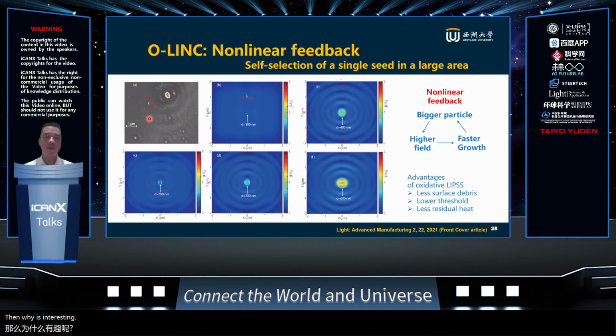Then why it's interesting is that we found that if we have a laser beam shining on this, they will generate a significant amount of scattering light. And if we look at it on the same scale, we find, and this is not surprising, that smaller nanoparticles have smaller scattering. Here it is 100, 200, 300, 400, 500, 600. You can see that the intensity of the scattered light becomes stronger and stronger, much more intense, with larger structures. And then we found that this is very interesting, because when we shine the light on top of it, these small oxidized nanoparticles will grow.